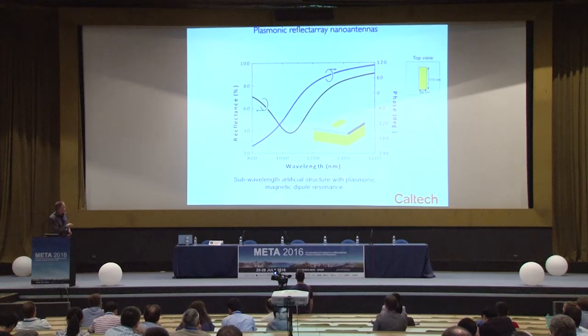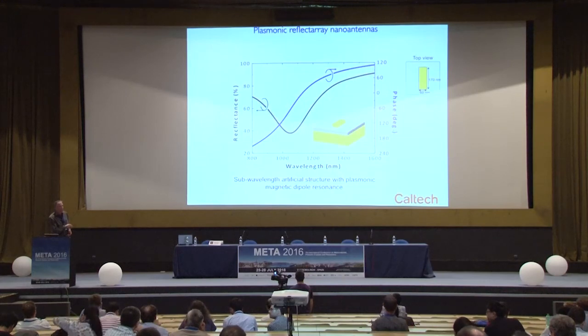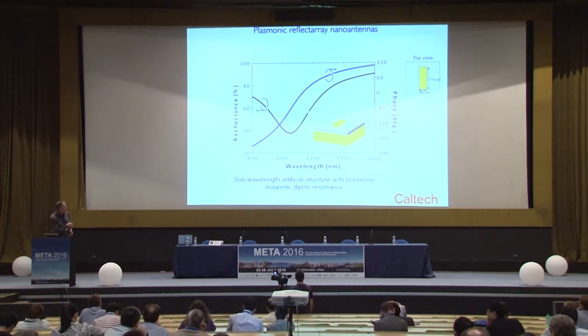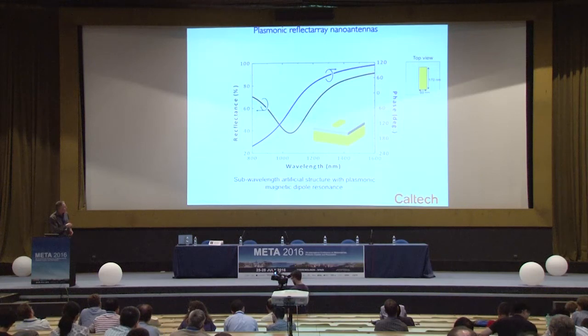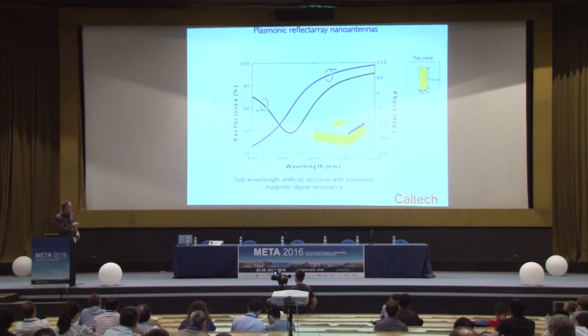This shaded band here is an indication of the ENZ response of our materials, which is now coinciding with the reflectance dip of the magnetic dipole resonance of this patch antenna. We can see here phase modulation, but you can see that the region where the phase shift is occurring, which is essentially a fundamental outcome of the coupling of the real and the imaginary part of the susceptibility of this structure, is now, of course, largest near resonance. With this kind of structure, I think the largest changes in phase, for example, are going to occur near the resonant absorption.